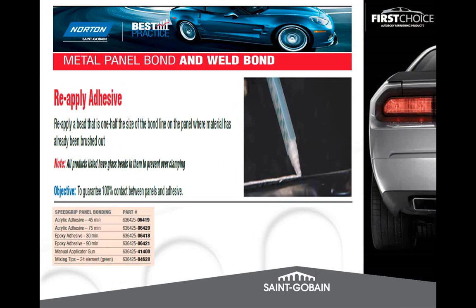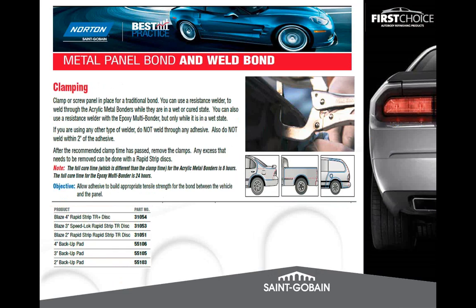So once we apply the adhesive, we clamp it into place. Screws can be used too, whatever your preference is, but the big thing is we want to hold it in place long enough for the glue to cure. Most of the adhesives, I know ours for sure, have the clamp time right on the front. So for example, a 90-minute glue might call for 4 hours of clamping time. That allows the adhesive to set up. If you screw it into place, then obviously it's going to be held there all along. If you resistant spot weld it, it's going to be held into place long enough for the glue to dry.